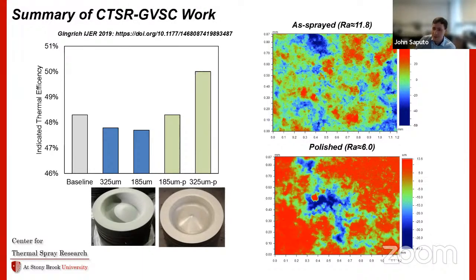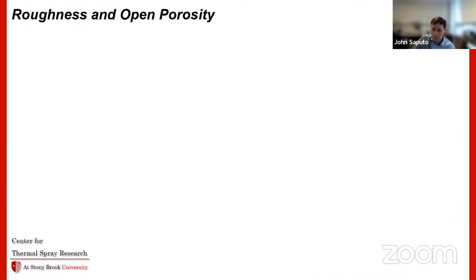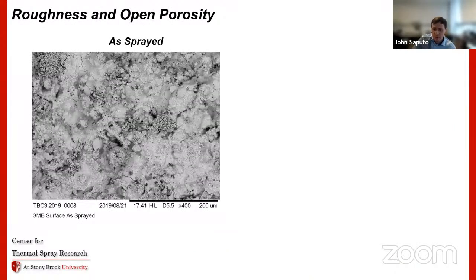So you can kind of see that it starts out really chaotic and random, and then as you polish, it turns into this nice plateaued surface with some pits across it. So we can clearly correlate that surface roughness effect to this performance in the engine, which is interesting. So our next thought in these systems was, hey, can we make this even better by making that surface even smoother? So the as-sprayed coatings, if you look at them in a SEM, look something like that.